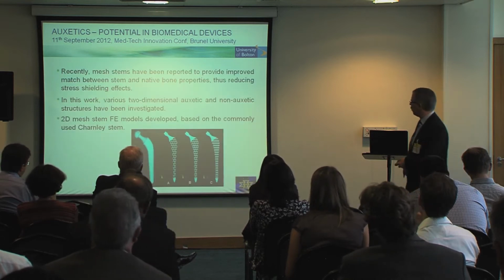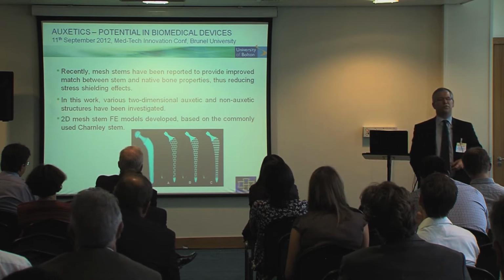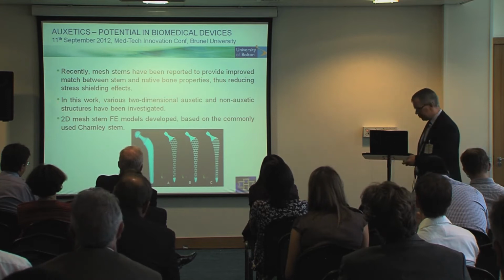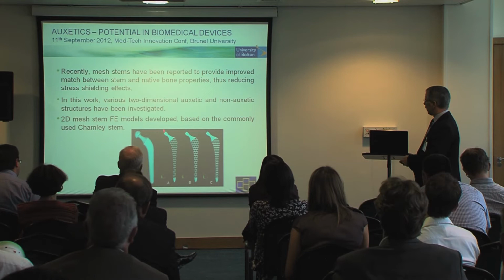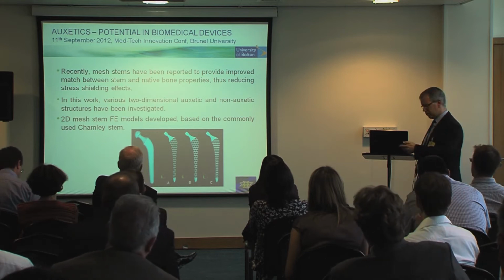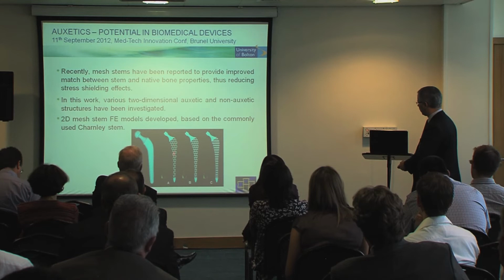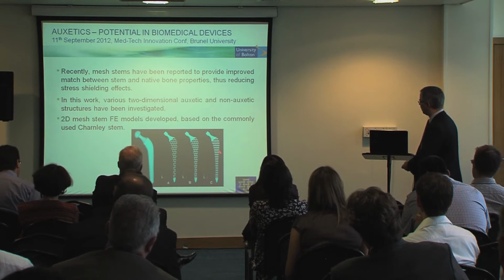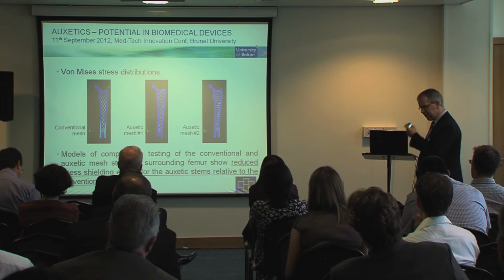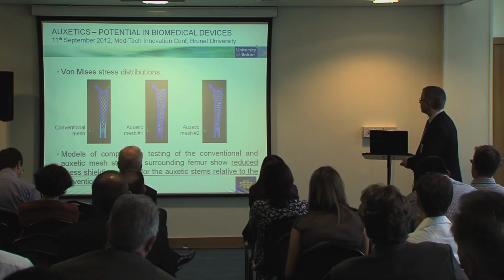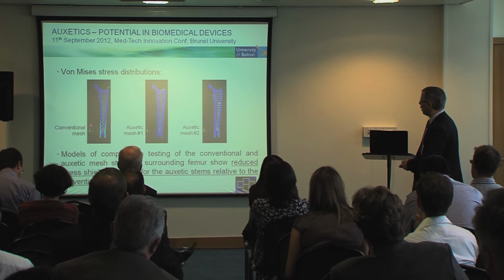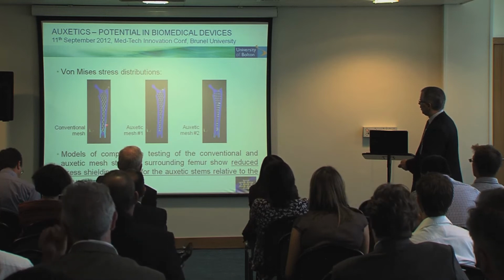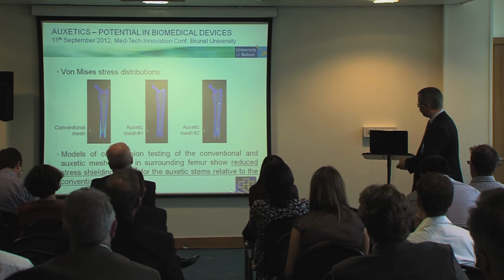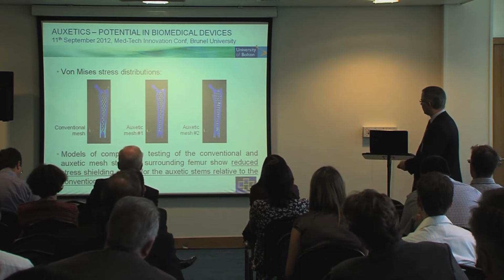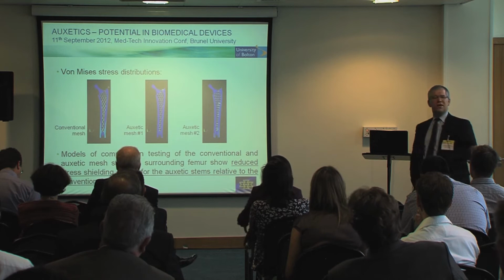Mesh stems have recently been reported where they get a better match to the mechanical properties of the bone. We're saying, okay, if you can get a mesh stem, we can look at altering the properties even further, not just to match the modulus, but we can play around with the Poisson's ratio. So this is a solid stem, this is a conventional mesh stem, and these are two auxetic mesh stems. And we've modelled those using finite element modelling, and you can see here for the mesh stem cases, the conventional one shows a build-up of stress in the bone at the distal end, whereas the build-up of stress is much reduced when you use the auxetic implants.